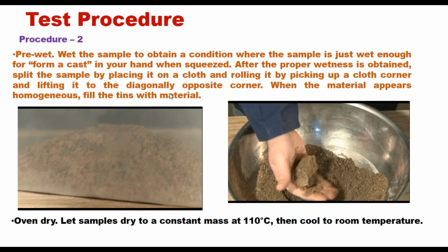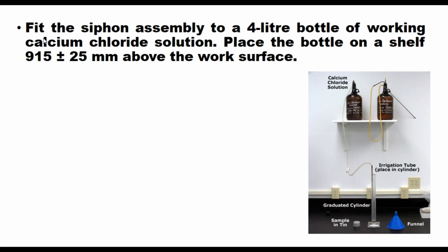In both cases, whether you prepare the specimen using procedure 1 or procedure 2, it is important to dry the sample at constant weight at 110 degrees centigrade and then cool it to room temperature. After that, fit the siphon assembly to a 4 liter bottle of working calcium chloride solution. Place this bottle on a shelf which is 915 plus minus 25 millimeter above the working surface.